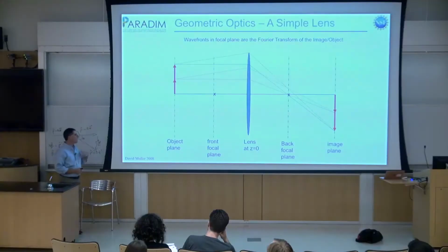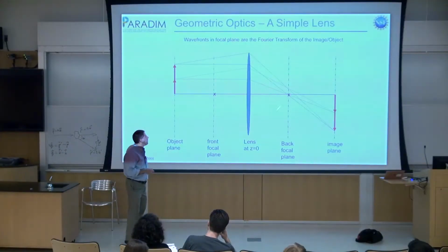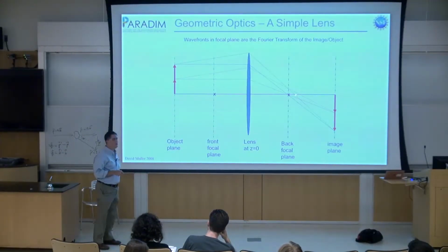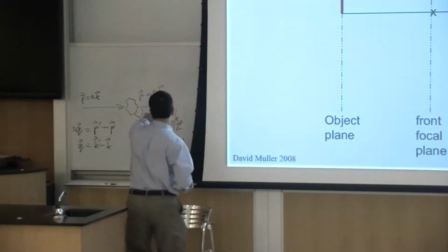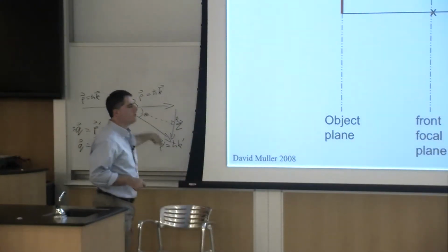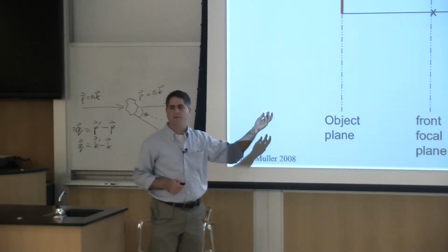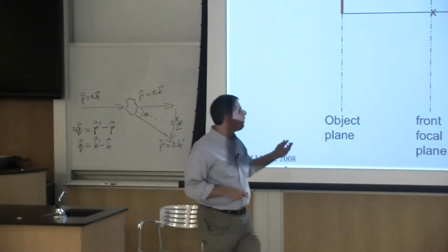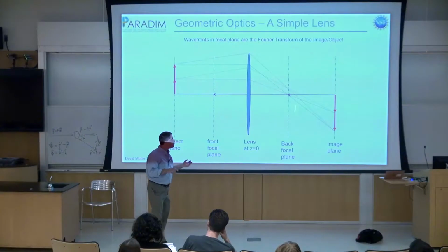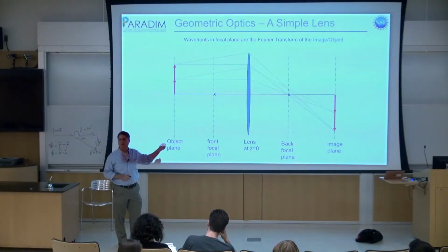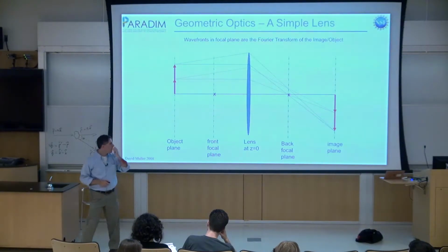So what happens in electron microscopes is, if I'm thinking of geometric optics, I keep talking in terms of angles, but all I have to do is remember this triangle, and I can very quickly turn my angle back into a momentum transfer. So the important thing about the back focal plane of the lens is that it's momentum space.